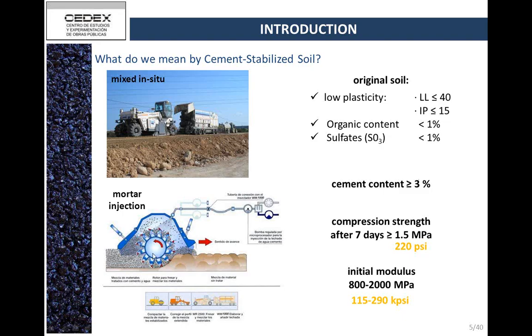And then we mix it in place. So this is a very big difference. We apply a cement mortar injection, we mix it in place, and then we compact it. Just to give an idea of this cement-stabilized soil, we require a compressive strength of 1.5 megapascal after 7 days. And the modulus values that we typically obtain from back calculation are between 800 and 2000 megapascal. So it is very high quality if we compare this material with a conventional soil, but it is not like a soil cement, for example. For a soil cement in Spain, you would use a very high quality soil, and then you would obtain a modulus which is around 10,000 megapascal. But for sure this is not a soil. This is something which goes further than a soil.